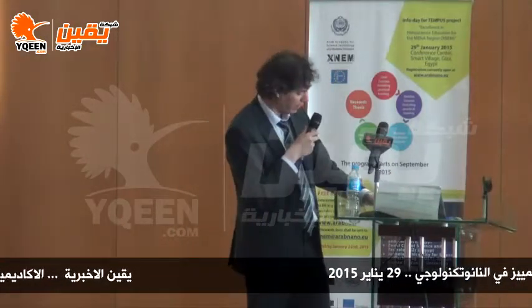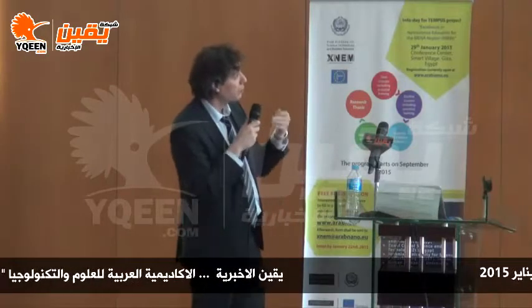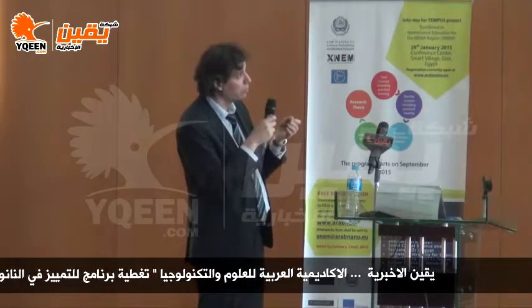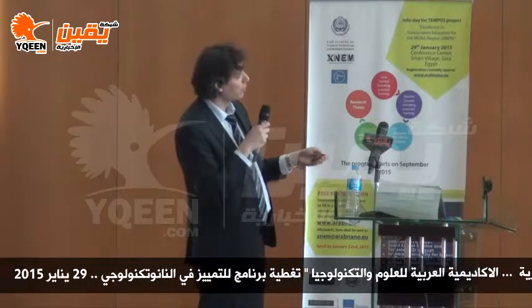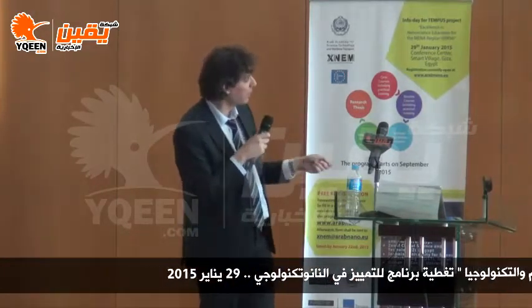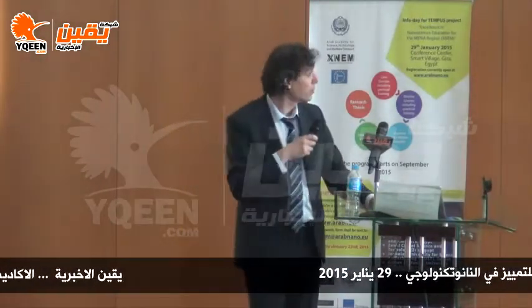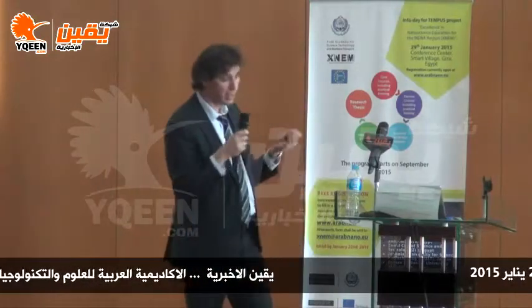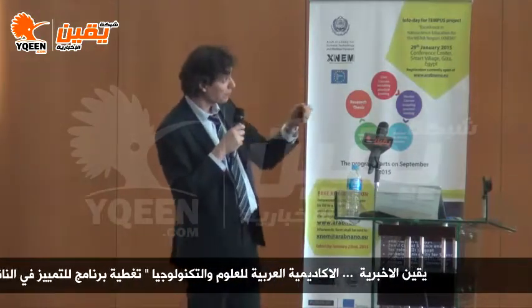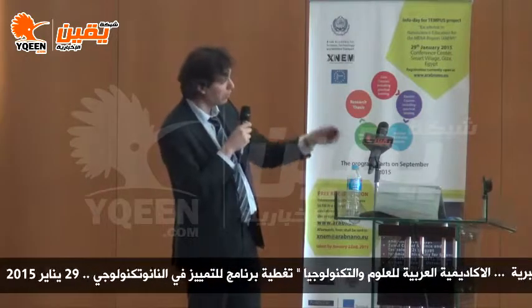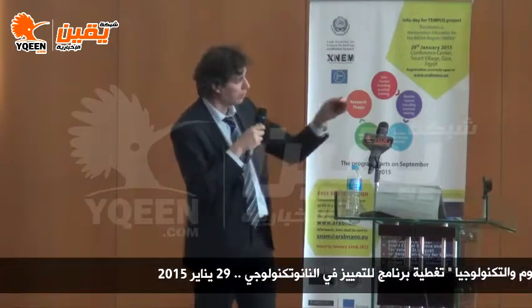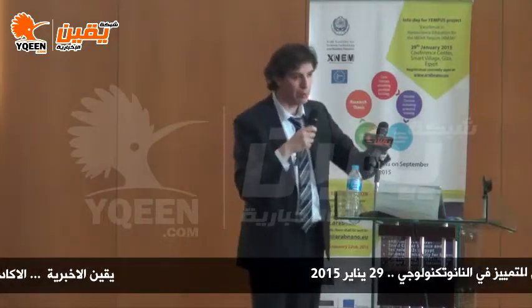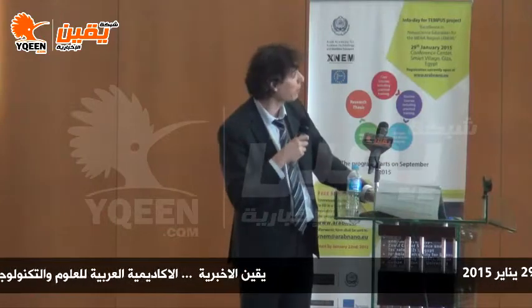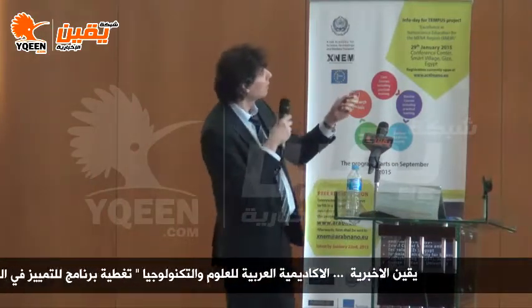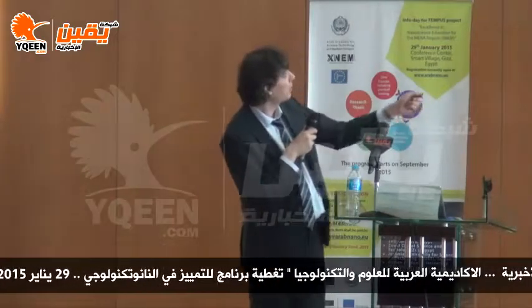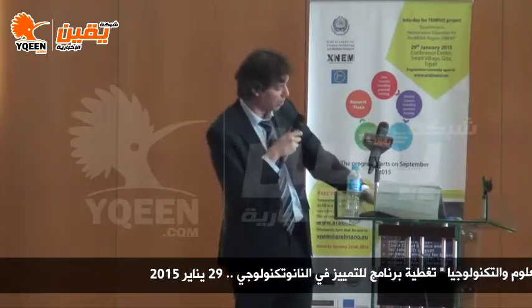Now the question is whether we can find an intermediate state, a compromise between sensitivity and leakage, making the photocurrent a little bit in between these two states while keeping a very low reverse current. So this is what we did here. We didn't change the diamond, but we changed the processing of the diamond. We decompose ozone within the plasma chamber on the surface of the diamond, for various times, from a few minutes up to more than half an hour. So starting from the initial state, we increase the decomposition of ozone onto diamond, and we check our devices.